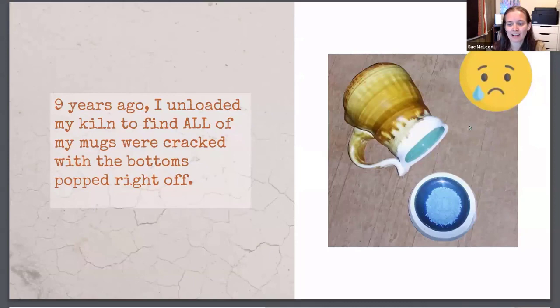I would put a clear glaze at the bottom to kind of catch the drips. But then I learned that the clear glaze had thermal expansion issues with the glaze on the inside, they didn't match. And so all my pots were broken.